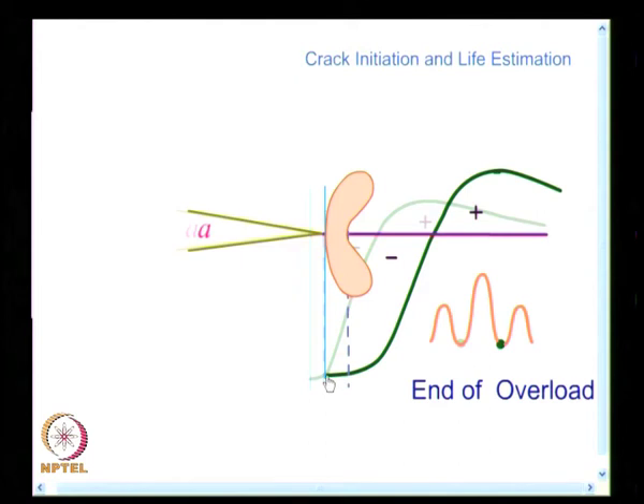So, what I have here is two pictures superimposed. I have initial crack length a, I have a small size of the plastic zone, then I have an overload. So, because of overload, what has happened? The crack has advanced by a small length delta a, plus you have a larger sized plastic zone at the crack tip, and the residual stress pattern now differs. I have a residual compression like this, and in the earlier case the residual compressive stress is like this.